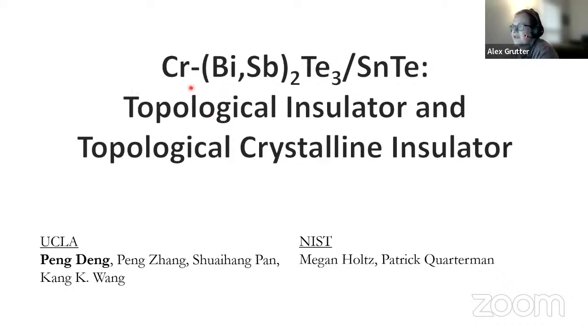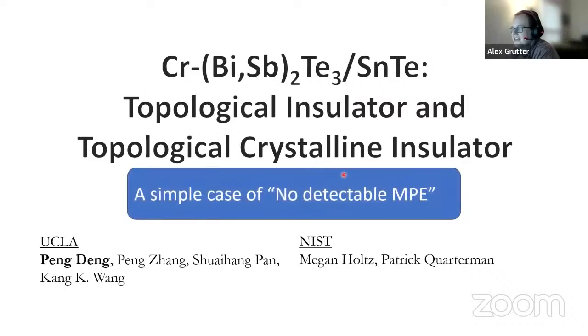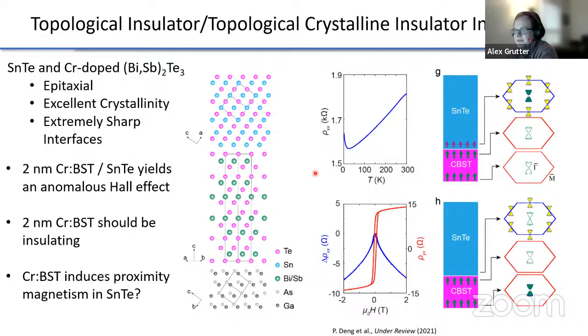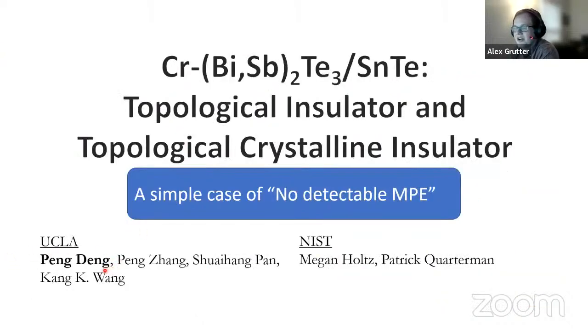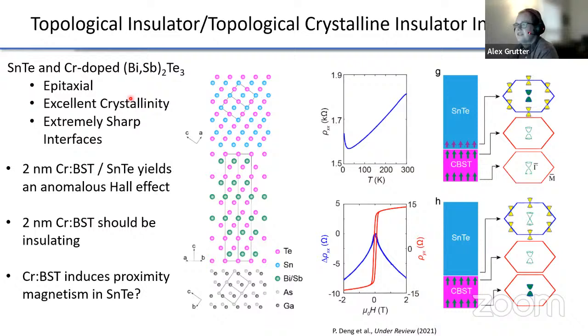Here we have chromium doped bismuth antimony telluride next to tin telluride. And this is a simple case of no detectable magnetic proximity effect. These materials are extremely nice. Tin telluride actually turns out to be a topological crystalline insulator. This isn't necessarily super important for the story I'm sharing, although the physics is very interesting. But the leader of the study, Peng Deng, grew these samples with really, really high quality. They're very growth compatible, and you have sharp interfaces with really great crystallinity.